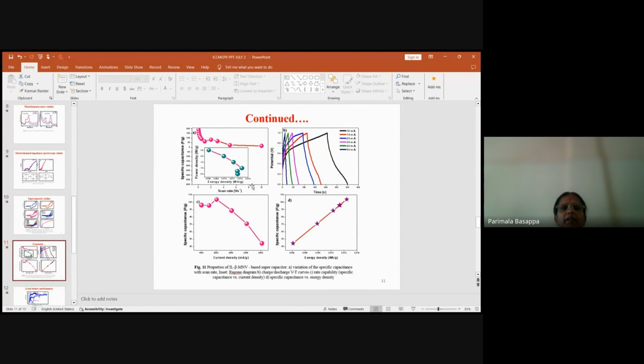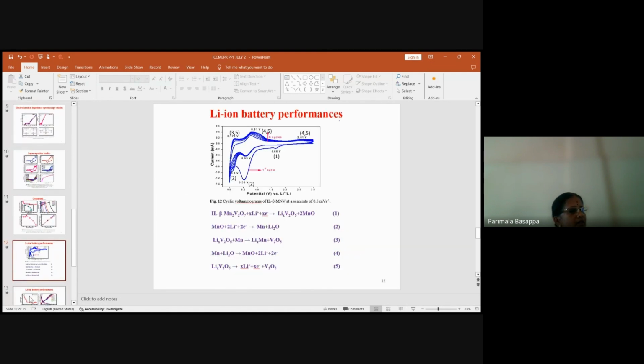So the scan rate, we have calculated the specific capacitance versus scan rate and specific capacity versus current density. You can see it is maximum at 2000 milliamperes per gram. And there you can see a linear plot in the case of specific capacitance versus energy density. Another thing we have carried out, the most important, is lithium-ion battery studies.